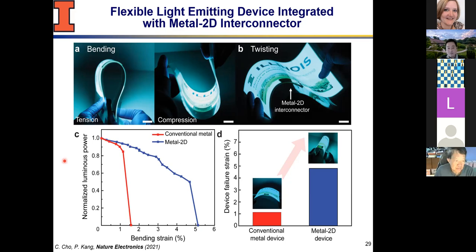So that's kind of what we're trying to do here. If you look at this C under bending, conventional, if you're causing certain strain, it gives you abrupt disconnection, whereas in our case here, you get a more stable region where it can tell you, okay, maybe we should think about examining our device as we measure the luminous power of the light emitting devices that we have created.